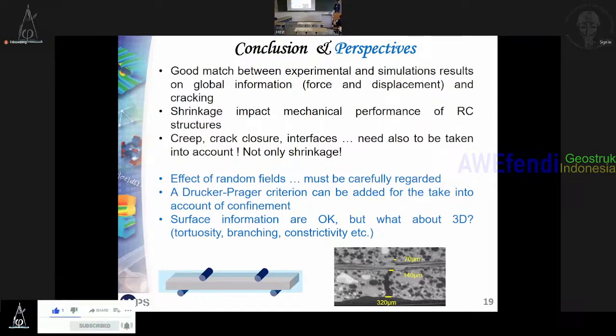Also, I've shown you that it's more or less okay to predict information at the surface, but as Dirk Schlicke said, here it's from tomography, so it was a glass fiber, not rebar. So as Dirk Schlicke said, you have an evolution of crack opening. Here it was in bending, that's why we do not have the symmetry, and you can see that the crack opening is almost equal to 0 just after the mesh. So it's not only crack opening at the surface, it's also crack opening along the crack, also the tortuosity, because it will affect the diffusion and the permeation, and also the constrictivity, the branching, etc. So it's not so easy.